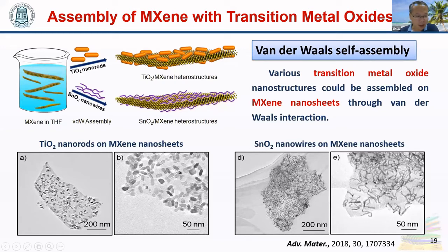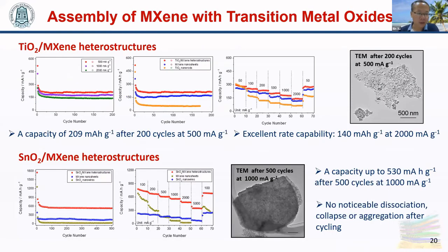In these composites, MXene provides good conductivity, alleviates the volume change of the metal oxides, and prevents the aggregation of nanostructures. And these nanomaterials can also prevent the restacking of MXene nanosheets. The synergy of these 2 components makes the heterostructures show very good lithium storage performance, especially cycle and rate performance. TEM observation indicates that no noticeable dissociation, collapse, or aggregation was observed after long cycle measurements. This confirms that MXene-based composites have very good structural stability.